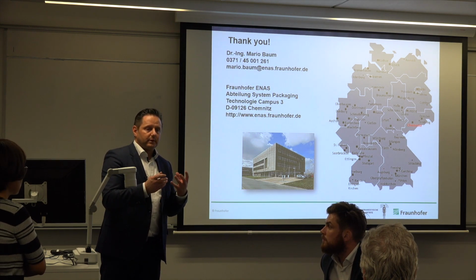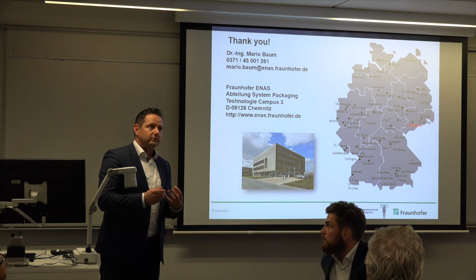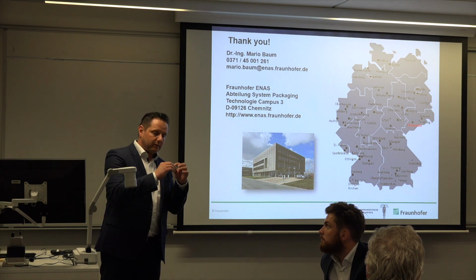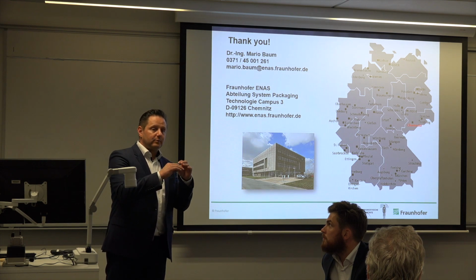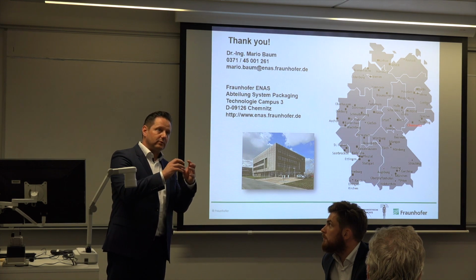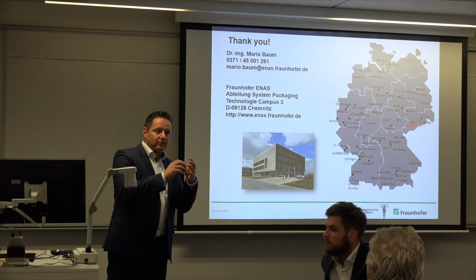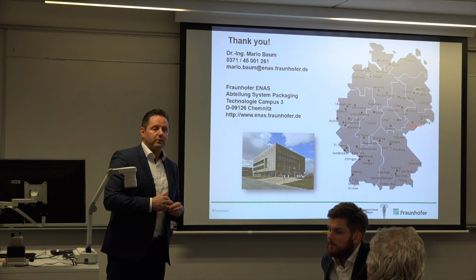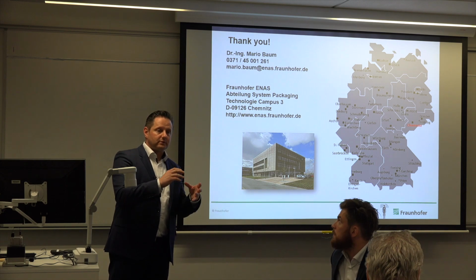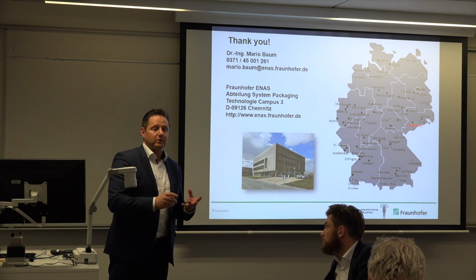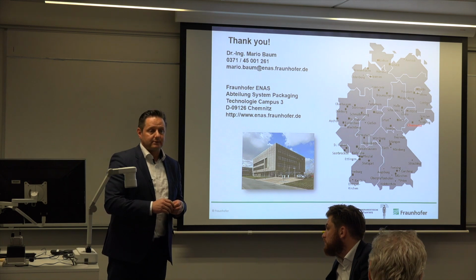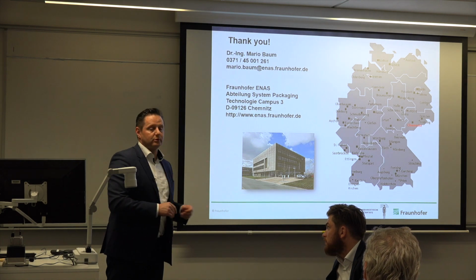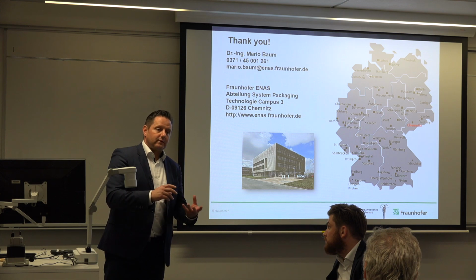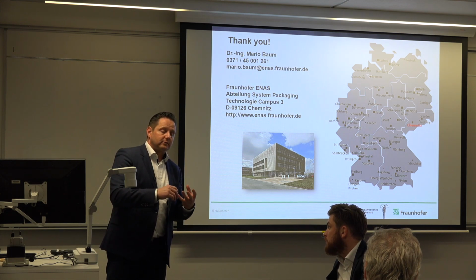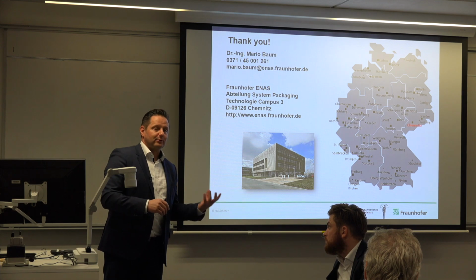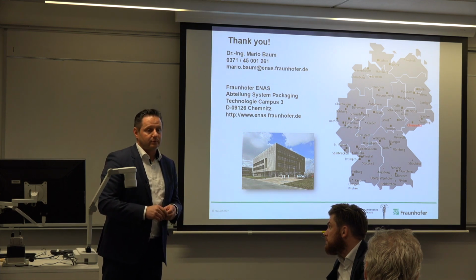And this was maybe one of the interesting points, that we have this quite thin, 50 nanometer thin layer, which increases the hermeticity of parylene to a significant number. The calcium was not changing the color, so it was really hermetically sealed within this test. The problem is I could not show it, because this was another project, another cooperation with another institute which created this test, and so I could not show the results within that project. But we think it's really promising.